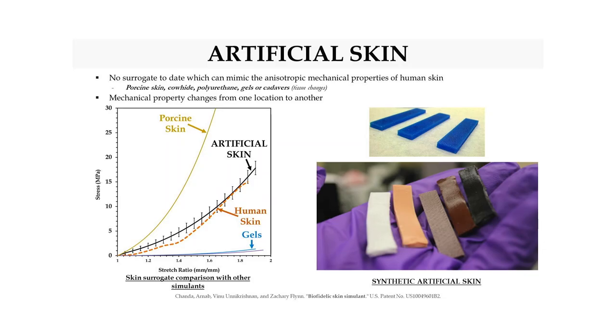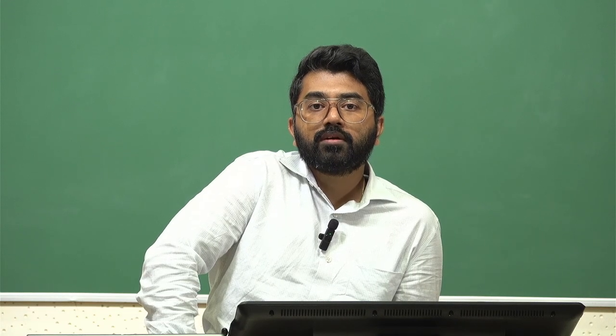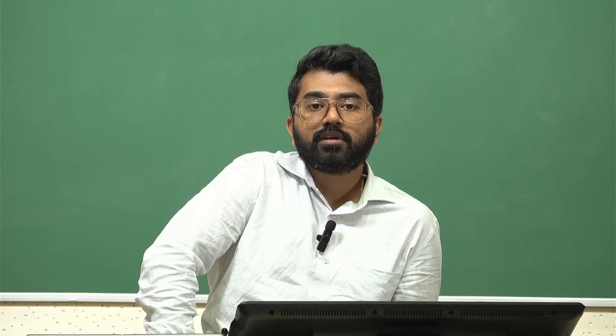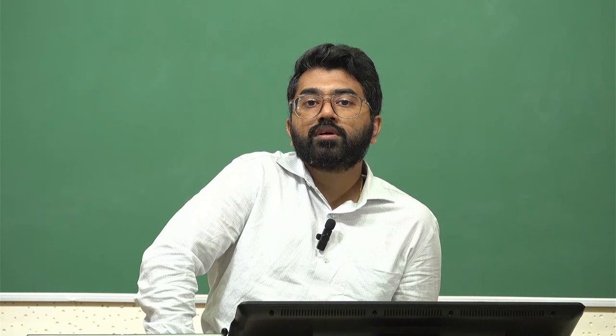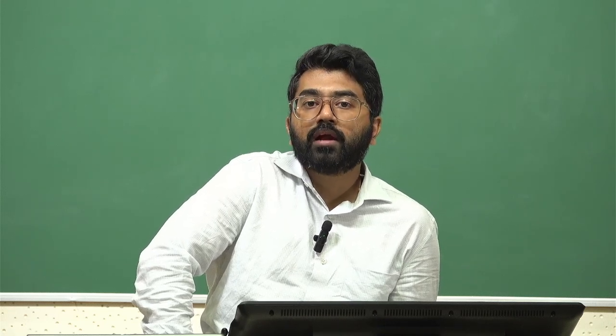The real human skin property is highlighted here with an almost orangish skin color, written as the human skin. So that is the human skin property approximately. Then you have the porcine skin property. We are looking at the stress-strain profile, or a stress-stretch profile. Stretch is nothing but strain plus one, just the plot shifted. If you look at the porcine skin property, it is much stiffer or stronger than the human skin. So that clearly indicates that if you use porcine or pig skin to run some experiments or analysis, it is going to give very different results from what human skin would give. That's why it's not a very good candidate.